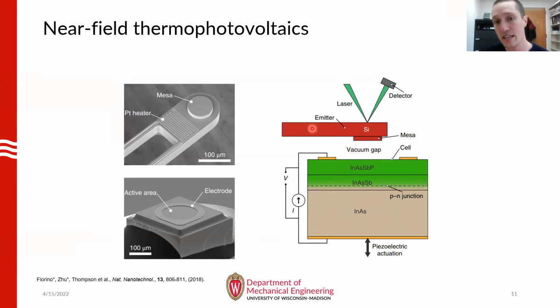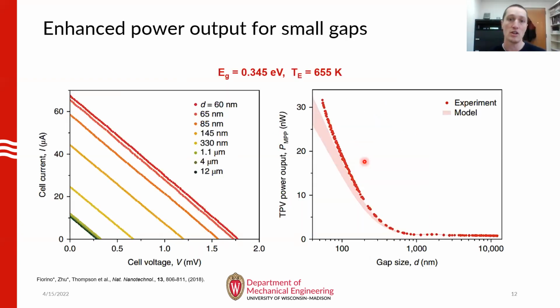And so after heating up the emitter by several hundred degrees, we could then perform IV sweeps of the PV cell in order to characterize its electrical power output. And we could do this while also stepping or systematically adjusting the gap size between them. So on this slide, you can see the central results of the experiment. Here, the emitter was at a fixed temperature of 655 Kelvin, and the band gap of the cell is around 0.35 eV. So on the left, you can see the measured IV sweeps of the PV cell for various values of the gap size.